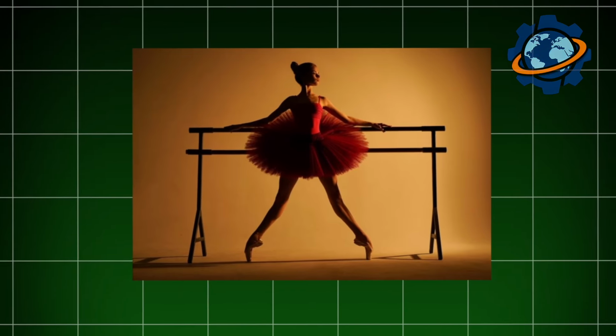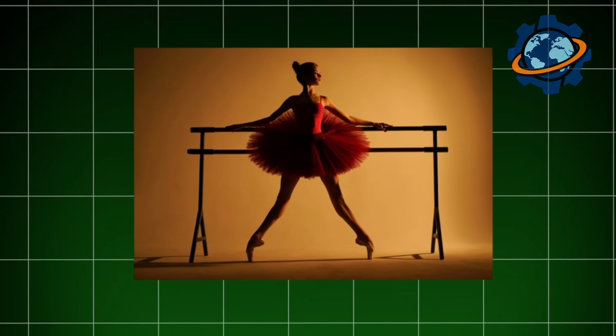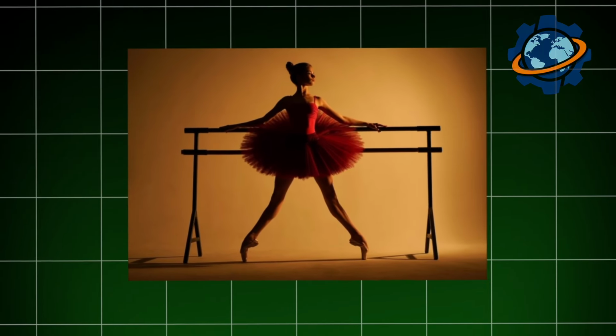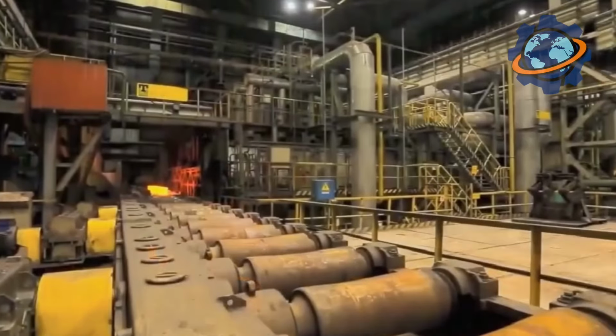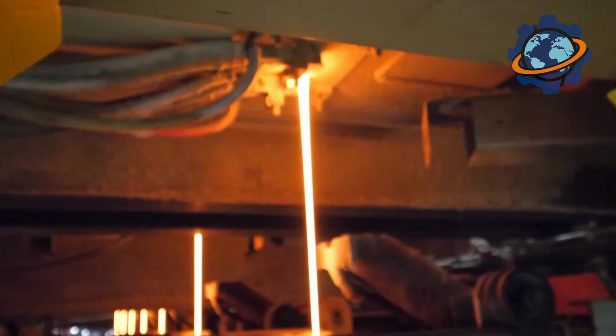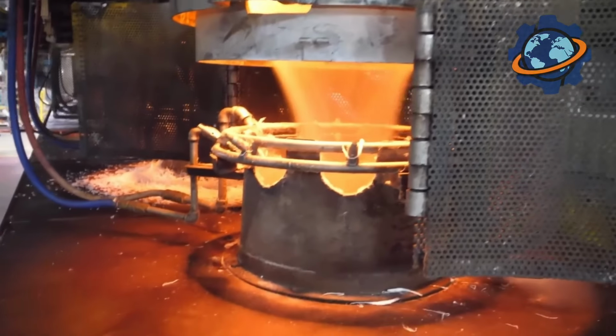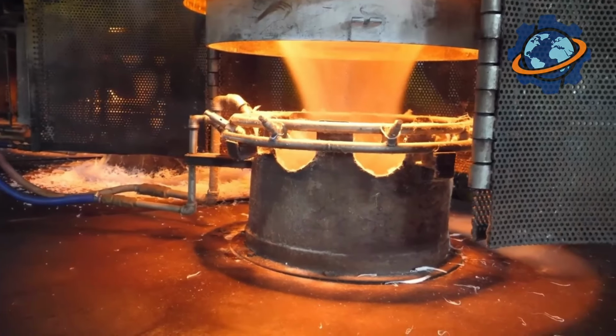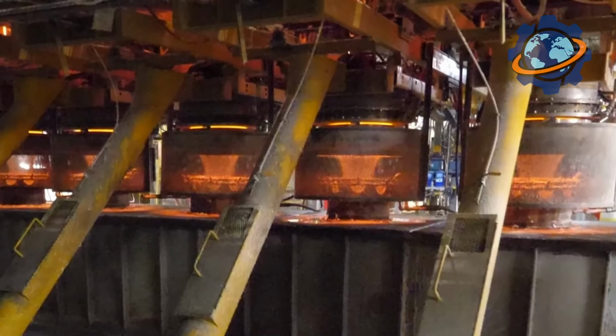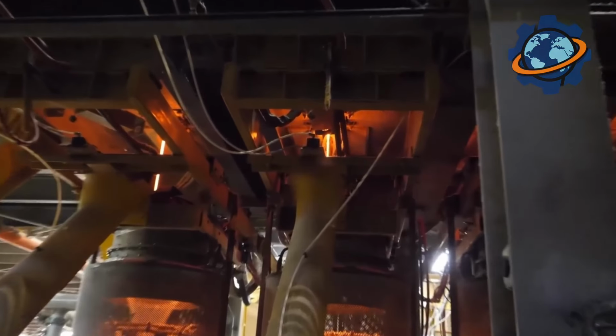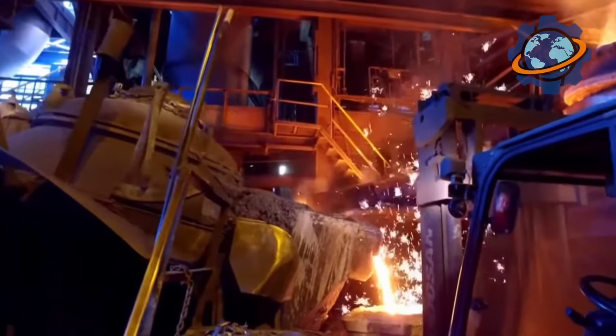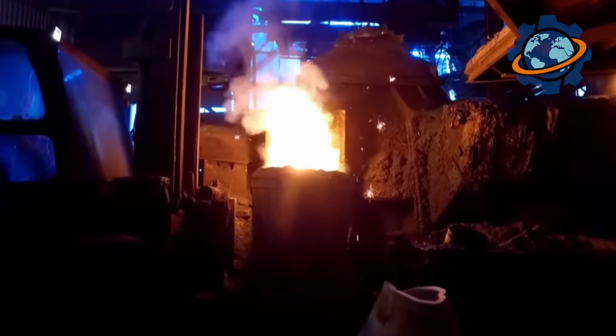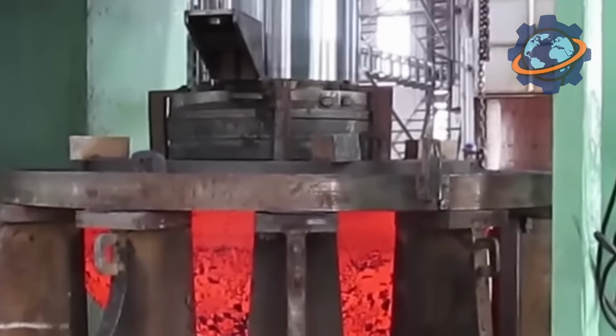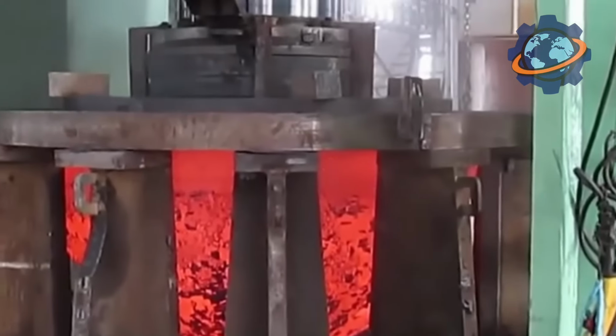The forging process requires balletic precision at colossal scale. After each press cycle, massive manipulators rotate the workpiece 7 degrees. Computer systems track rotation angle to within 0.1 degrees. Because uneven forging creates thickness variations leading to stress concentration, the ingot must be reshaped uniformly, ensuring wall thickness varies less than 1% across the entire vessel.